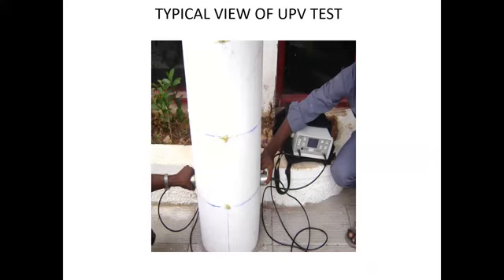Now, what is more important here is that the transducer frequency you choose matters a lot. Depending upon the path length, you need to go with the natural frequency. The lower the natural frequency, the higher the distance traveled. So if the thickness of the member is going to be more and more, you should always opt for lower natural frequency transducers. Otherwise, you may not get a proper reading. Generally, homogeneity of the concrete can be verified with this, presence of voids, cracks, and loss of integrity. Qualitative, as I said, and relatively, concrete conditions can be obtained.